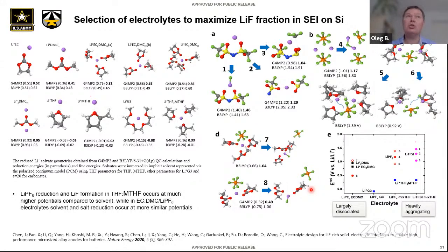However, what is challenging there is how to take into account this extra reduction in a porous species, mass transfer limitations. SEI, in my view, forms in seconds, minutes. And this mass transport limitation, if you do coarse graining, where it's much faster, then relative rates are also different. So it's a challenge. It is a challenge, and that's why with limited resources we stick with the initial stages. Okay, thanks for this.